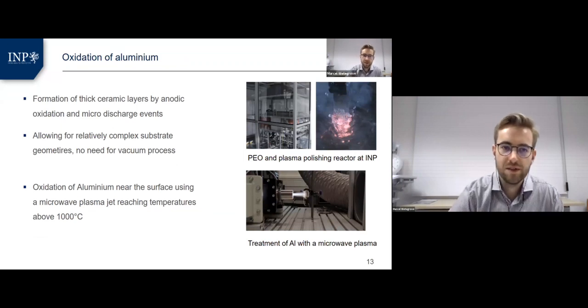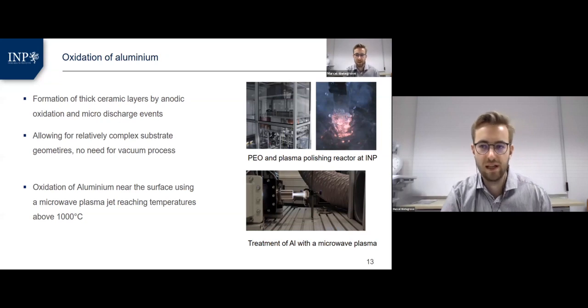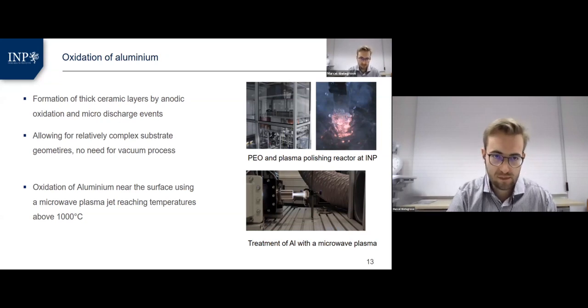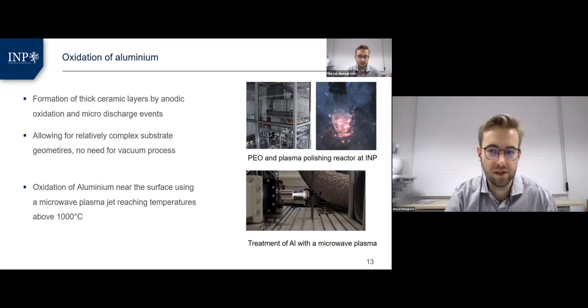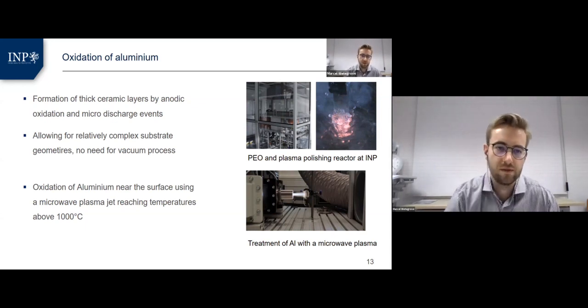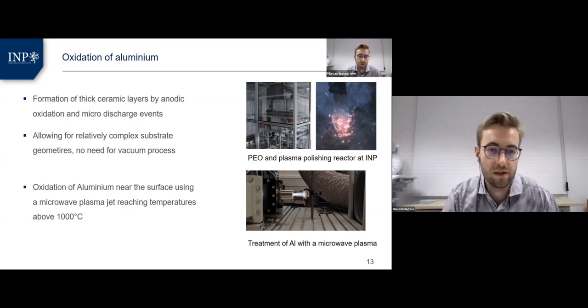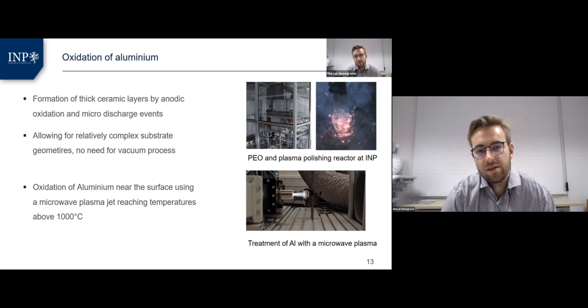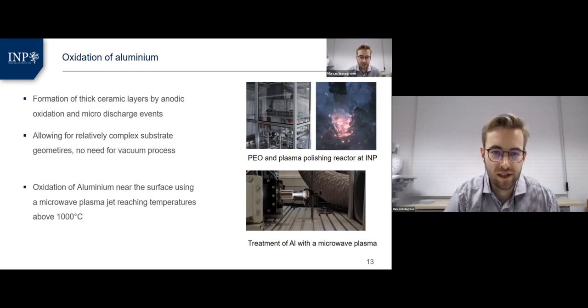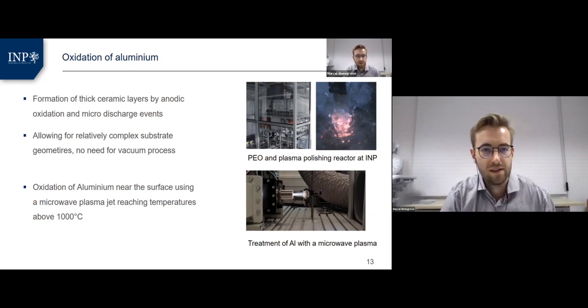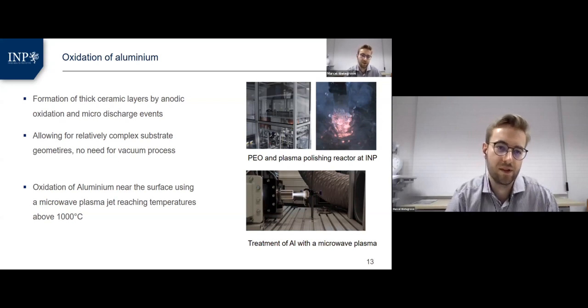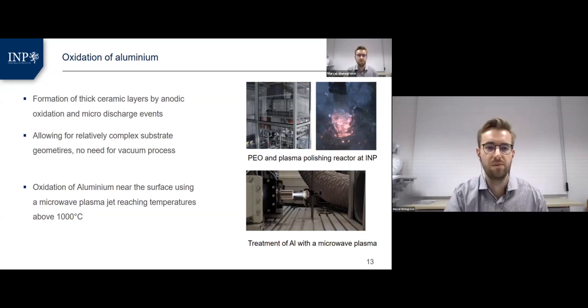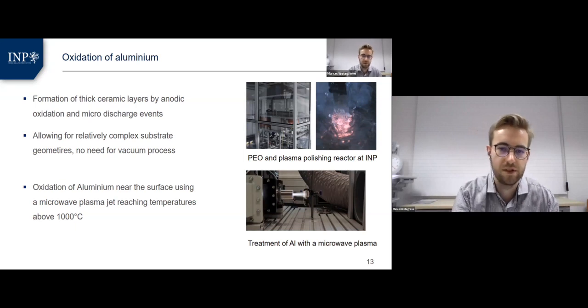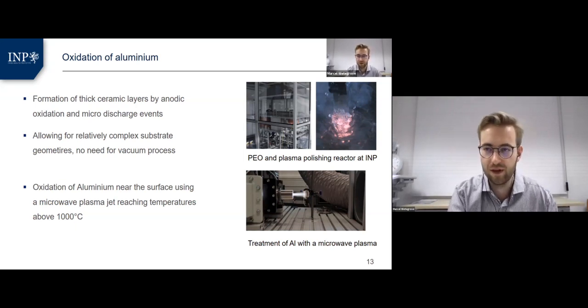Another field that we are looking into is the formation of aluminum oxide layers on aluminum substrates by using plasma electrolytic oxidation, which is a relatively straightforward method, which is environmentally friendly and allows us to coat relatively complex substrate geometries and avoids the need for vacuum processes. And here, thick ceramic layers can be formed by anodic oxidation and micro discharges. Also, we aim to oxidize aluminium near the surface using microwave plasma jets, which are able to reach temperatures in excess of 1000 degrees Celsius.